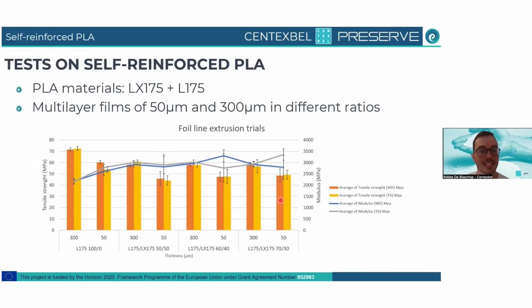Then I go over to the self-reinforced materials. So we look at PLA, two different types of PLA that you combine together. You have an amorphous PLA, the LX175 here, and then a semi-crystalline PLA, here the L175. And you actually use these together in a multi-layer film. We have used two different thicknesses of films, one of 50 microns that is more for the packaging side, but also a 300 micron one that is used for thermoforming. And this is very important as well.